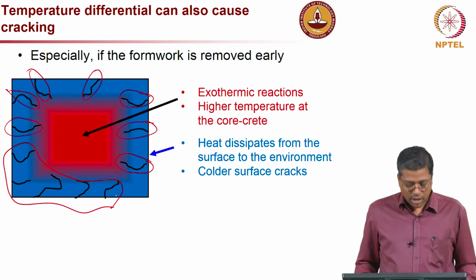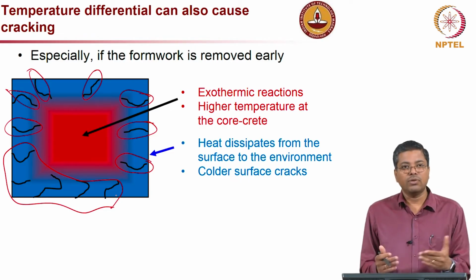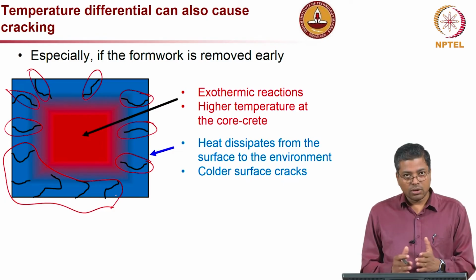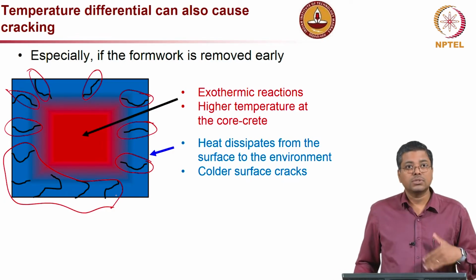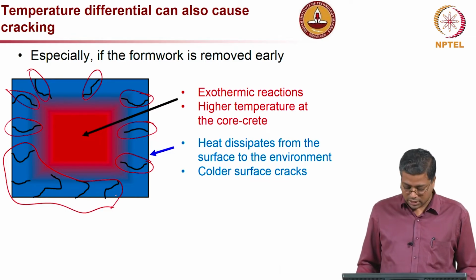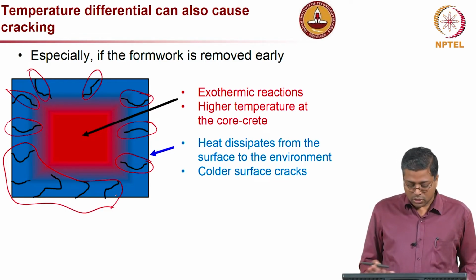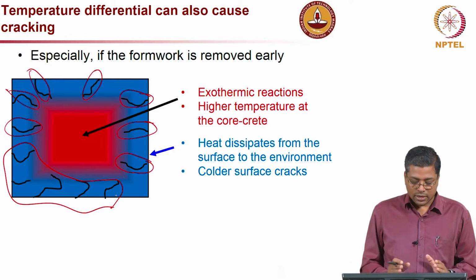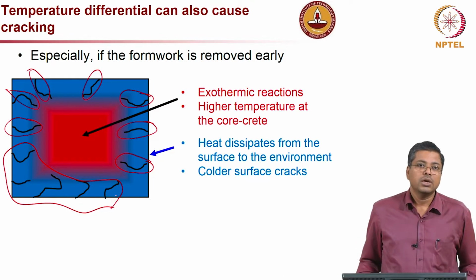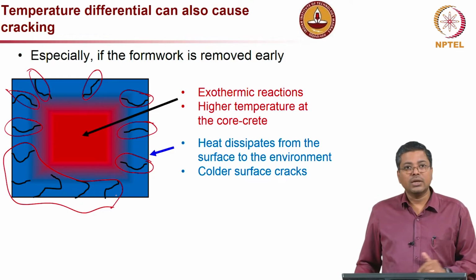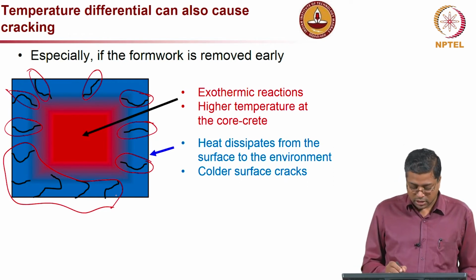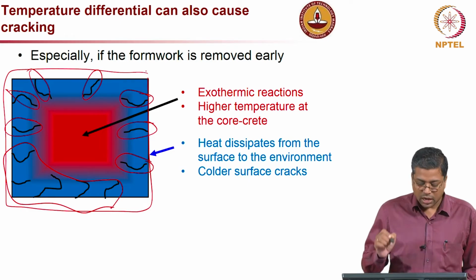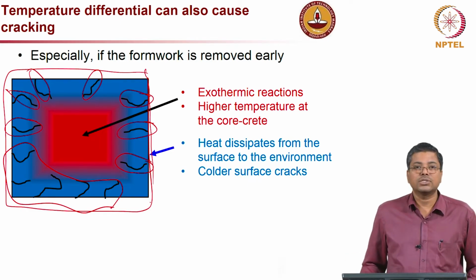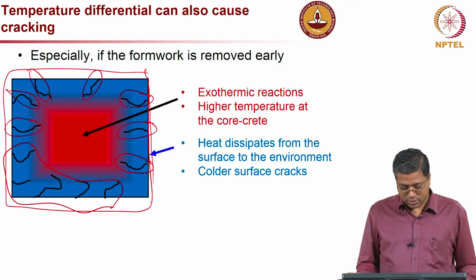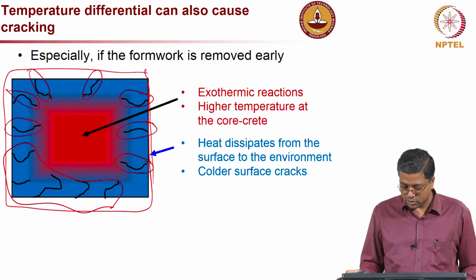So, the cracking might happen at the peripheral region, and imagine now a case where you have cracking and you have reinforcement near the cover concrete, you might have corrosion related problems at a later stage. So, you do not want the concrete to crack. How do you ensure that this does not happen? By making sure that the heat generated inside is not lost into the atmosphere. So, you have to maintain a good formwork and a good insulation around the peripheral region. The concrete has to be covered with a good blanket or some such measures, which we will also talk about later.